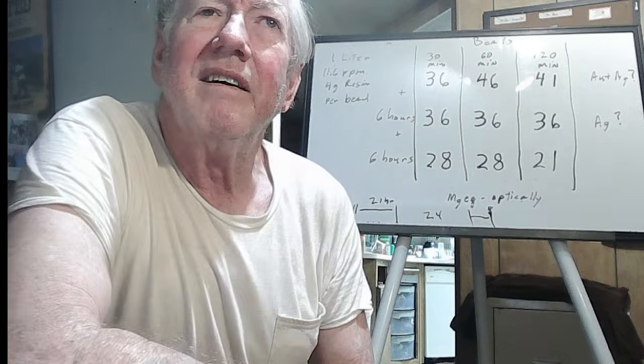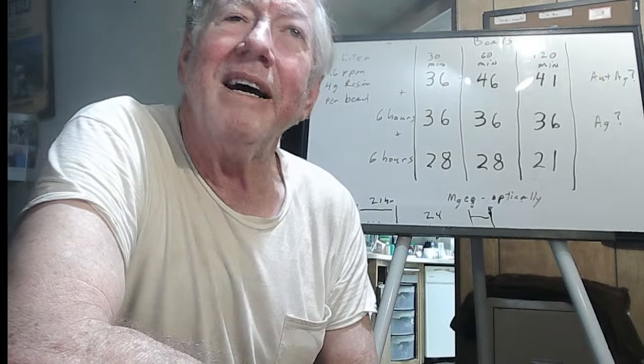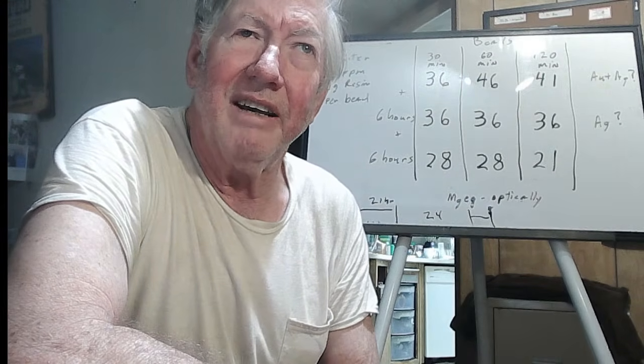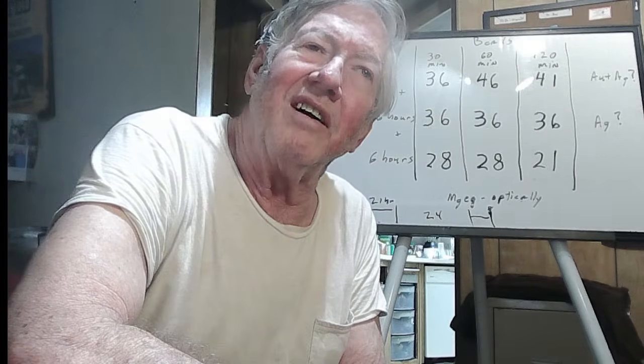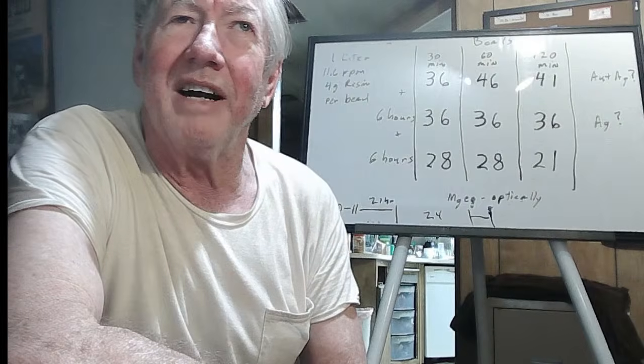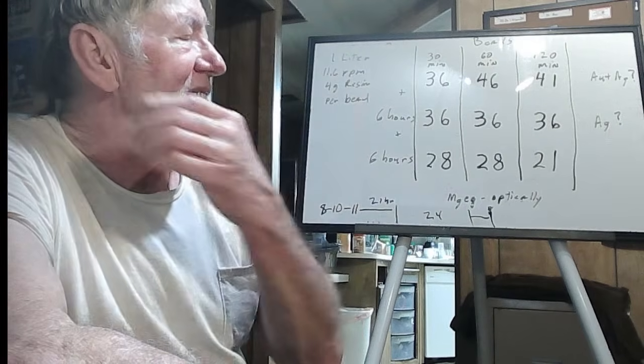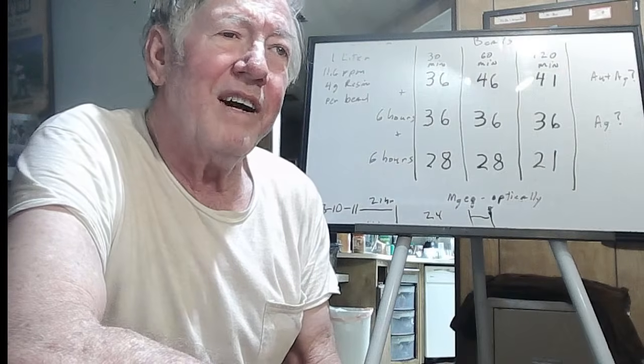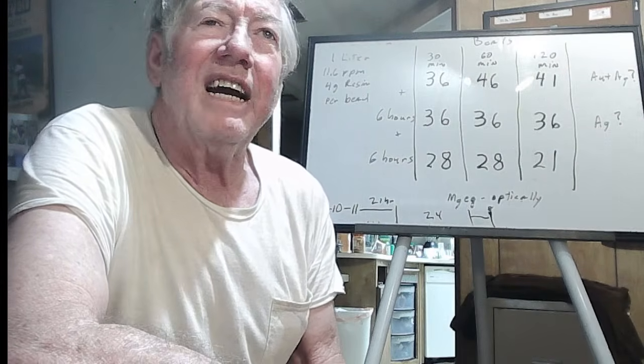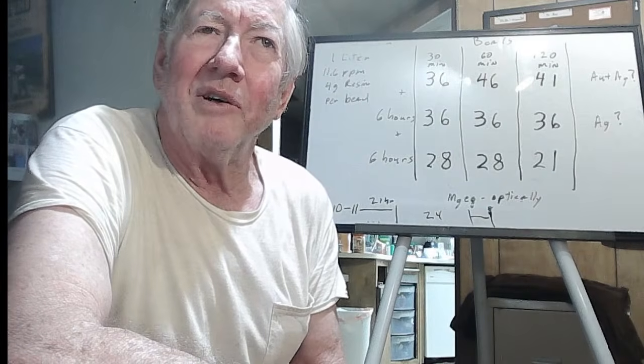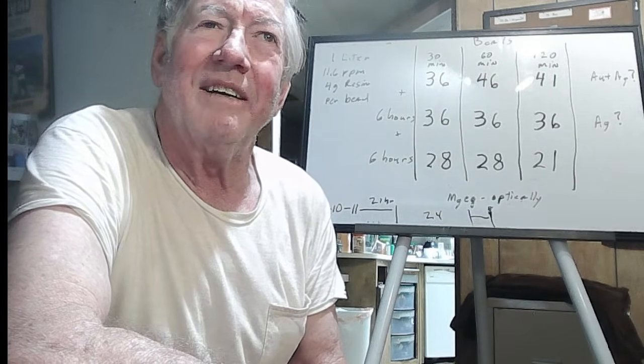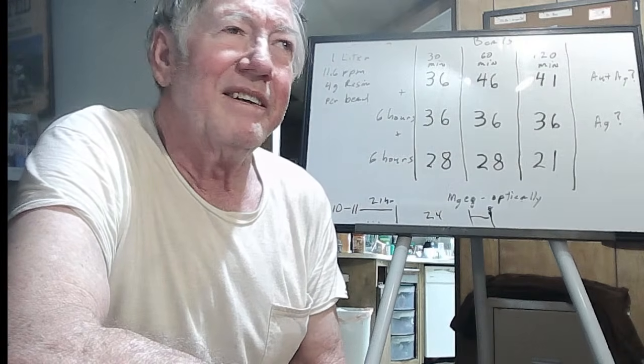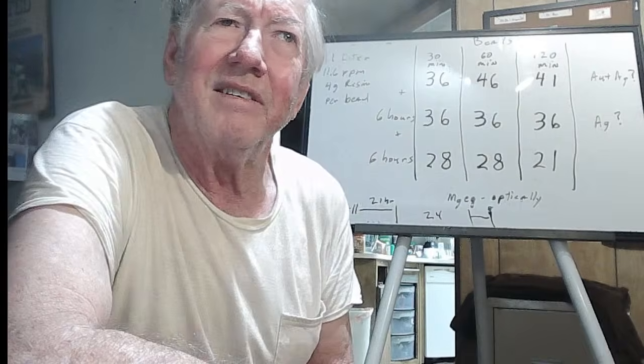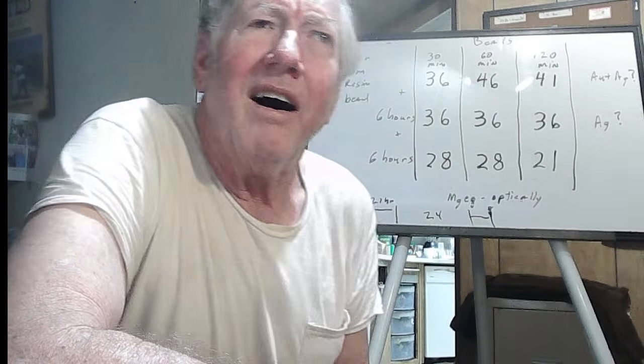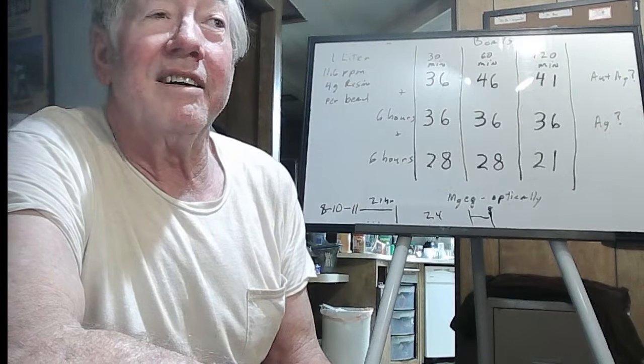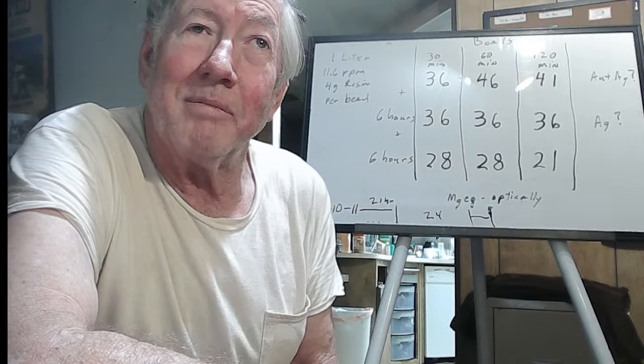Yes, the Goldex is best for very fine gold. The finer the gold, the more you want to dissolve it. The coarser the gold, the more you want to gravity separate it. We did testing out at the mill where we found that the Eco Goldex started to have problems at about 100 mesh gold. It wasn't dissolving it in any reasonable period of time. It took like a week or more to do that. On the other hand, 100 mesh gold is easy to get by gravity separation.